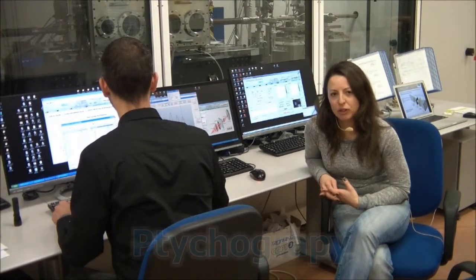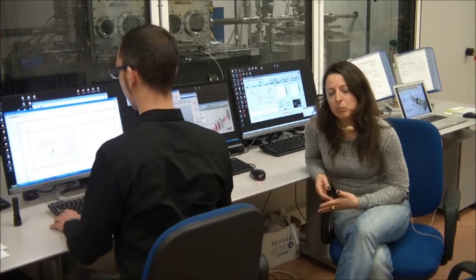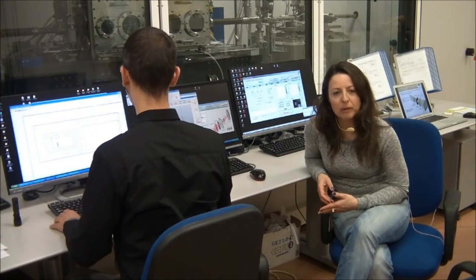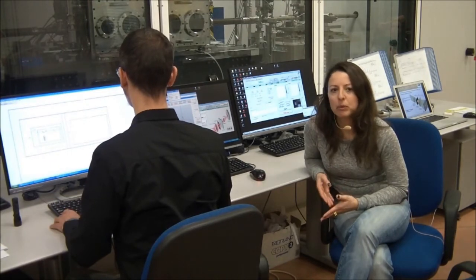Recently in TwinMic we tested an innovative X-ray imaging method called ptychography. Ptychography is evolving rapidly into an important X-ray imaging tool. It can be performed with X-ray optics or as a lensless imaging mode, and in both cases it can provide a spatial resolution better than the limit imposed by the system.